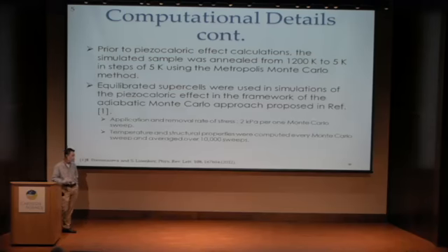The process is very natural for caloric calculations. It allows us to simulate first order and second order transitions, irreversible and reversible processes, and metastable and stable phases. Some details concerning this approach: our application and removal rate of stress is 2 kilopascals per Monte Carlo sweep. This value is relatively small compared to the maximum stress field that we applied of 2 gigapascals. The temperature and structural properties are computed every Monte Carlo sweep and averaged over 10,000 Monte Carlo sweeps.